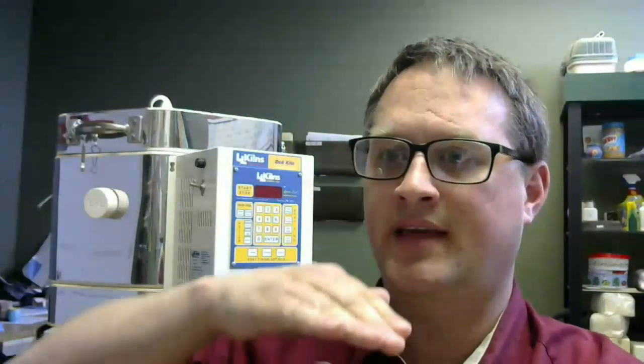What causes blistering in a glaze load? We'll definitely touch base on that tomorrow as well. We can talk about all sorts of things like pinholing and crazing and blistering. But really quickly, blistering in a glaze load is going to come from two sources. It's going to come from not a long enough bisque in the bisque fire. So those outgasses are going to create a bubble of gas between the clay and the glaze layer. You can also get blistering or pinholing if the glaze is too thick. And then that we can talk about tomorrow.